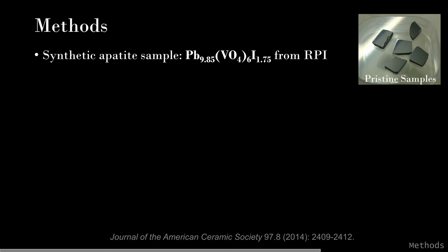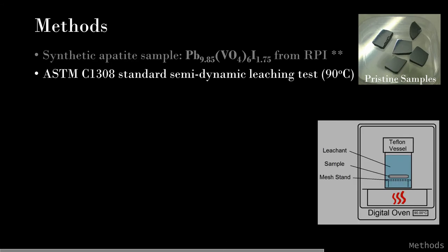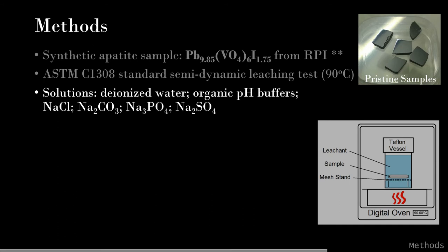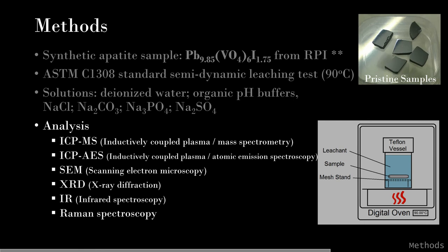Our sample is lead-vanadate-iodo-apatite, synthesized by our collaborator from RPI. A standard semi-dynamic leaching test protocol was applied: a sample pellet was placed on a mesh stand in a Teflon vessel, and every 24 hours the reacted solution was fully extracted and replaced with fresh solution. Leaching tests were carried out in different solutions including deionized water, organic pH buffer, sodium chloride, sodium carbonate, sodium phosphate, and sodium sulfate. Reacted solutions were analyzed by ICP-MS and ICP-AES, and leached surfaces were examined by SEM, XRD, infrared, and Raman spectroscopy.